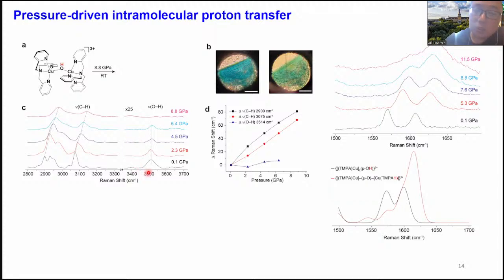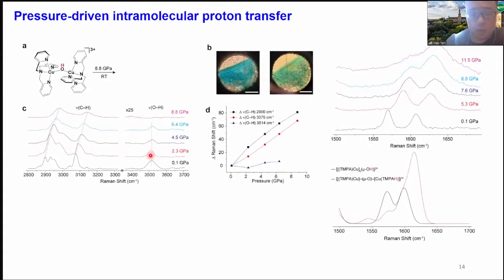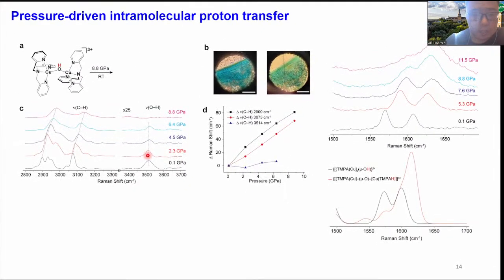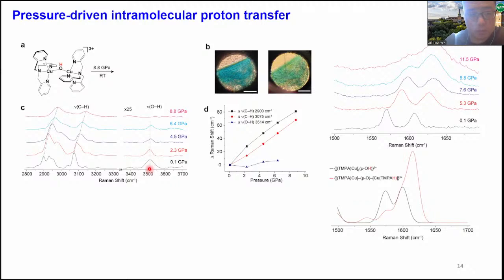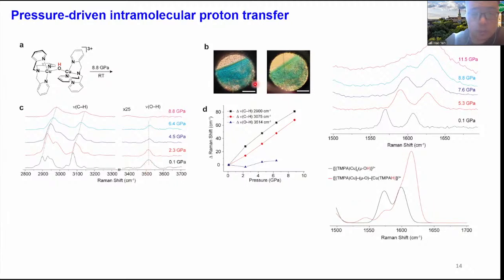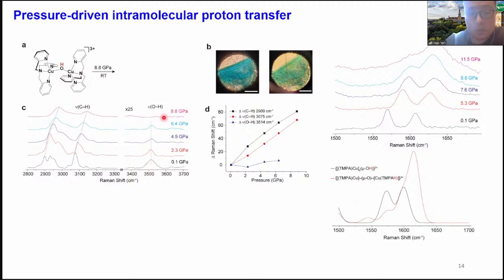We can trace the structural changes by Raman spectroscopy. For example, you see here that the stretching mode of the OH bond remains stationary against a otherwise universal blue shift of other vibrations due to mechanical stiffening of the chemical bonds. And at the same pressure, when the color change happens, this vibrational band disappears.